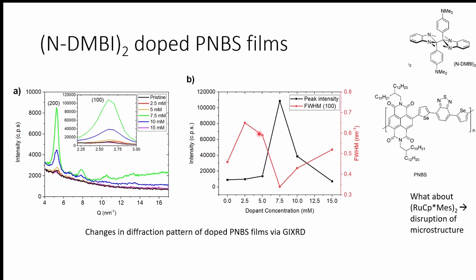But these dopants can go wherever they want. They can go into the amorphous region. They can go into the crystalline region. So it seems that at this concentration, at 7.5, there is a sweet spot of distribution in my film where you just get a crystalline material, and then beyond that, the peaks start widening again, just due to excessive dopant. Because as I mentioned earlier, these two structures do not like each other, so they will try to phase separate if they have the option.